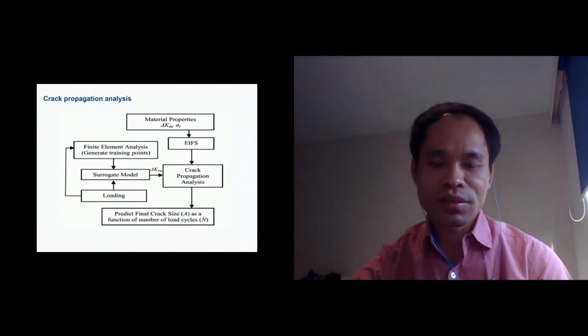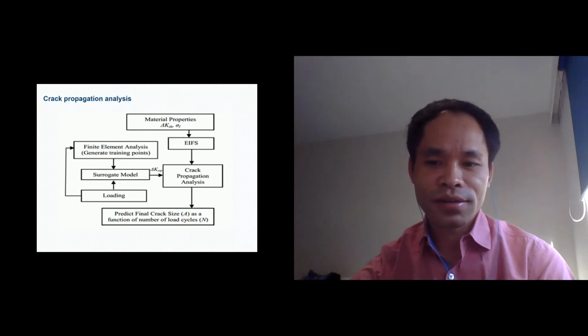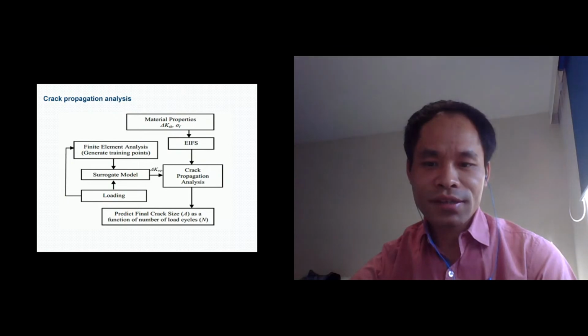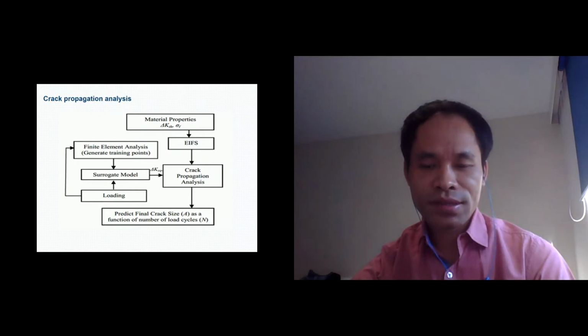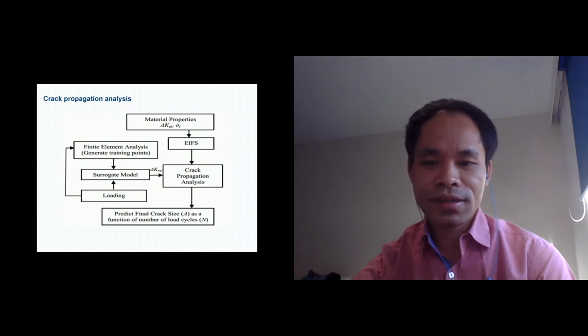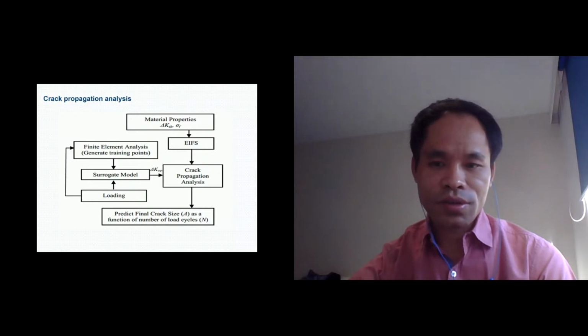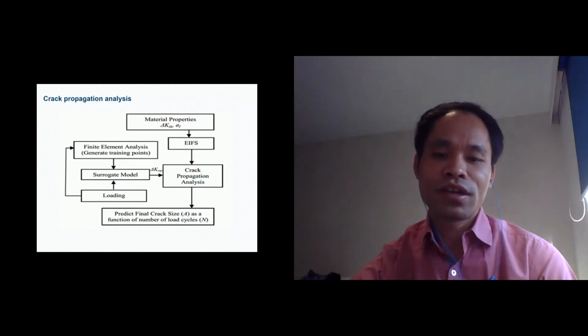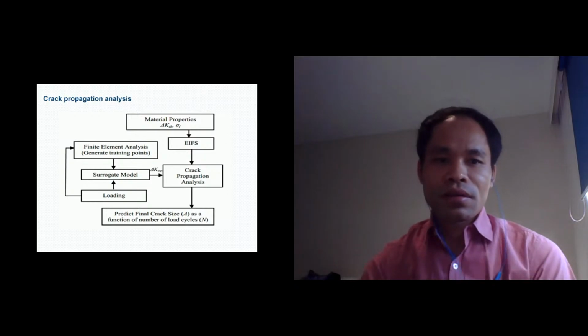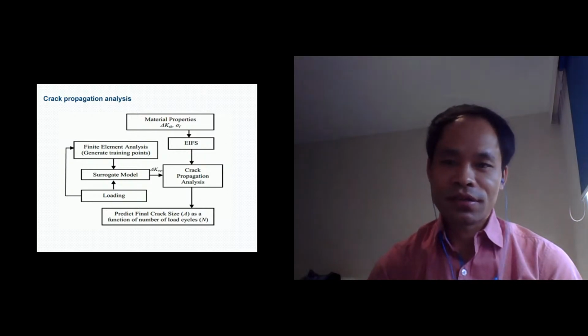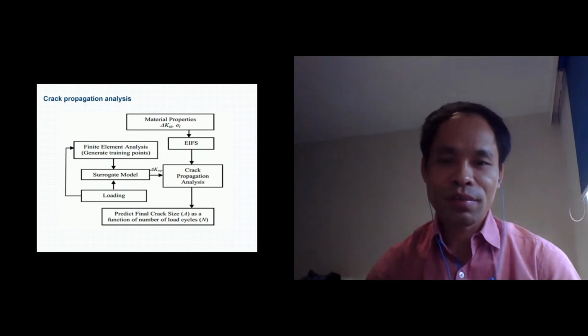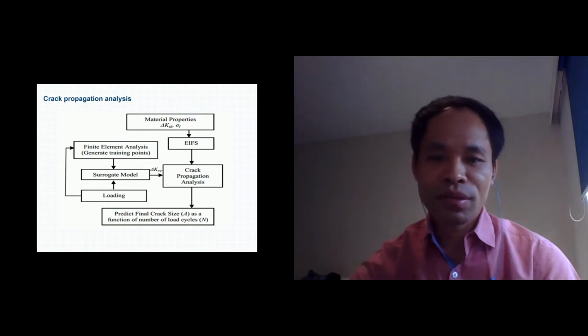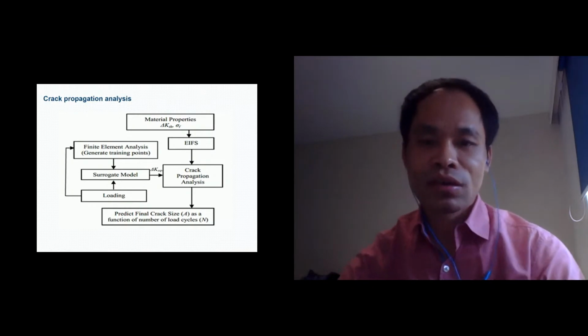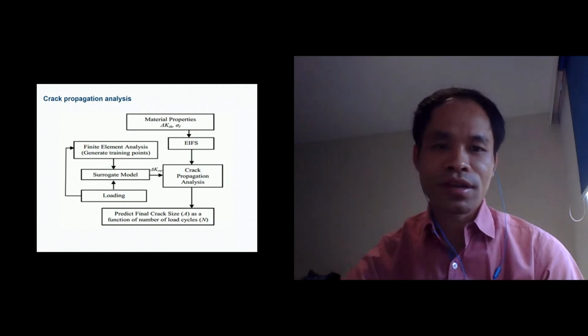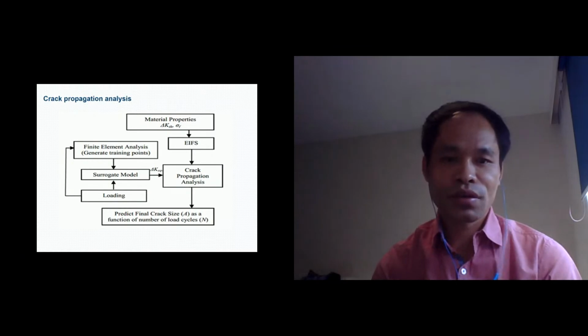However, this research also mentioned that there are many sources of uncertainty. Those uncertainties are the loadings, initial flaw size, data uncertainty, and model uncertainty, like the crack growth law and correct calculation of stress intensity factors, and all of these have an individual effect on crack growth prediction. Now, all these crack propagation analyses and crack growth laws exist, but how about considering the temperature? Temperature has an impact on the material properties, especially the toughness of the material. So now I just want to include the effect of temperature on fracture toughness.